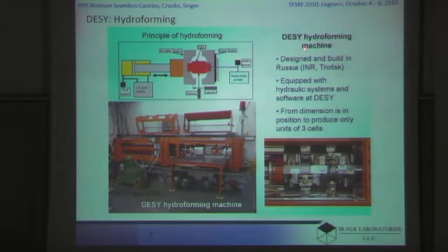This particular one at DESY was manufactured in Russia and modified at DESY, and uses a hydraulic system with oil and a water hydraulic system. The irises are placed at a larger distance than they are in the final product, and moving dies are used to push the irises together as the interior of the tube is expanded. You can see some copper pieces here, and copper is the method of choice for experiments because it's a lot cheaper than niobium. And the hydraulic system, oil hydraulic, is used to press these dies together, and they're expanded inside the aluminum dies shown here.